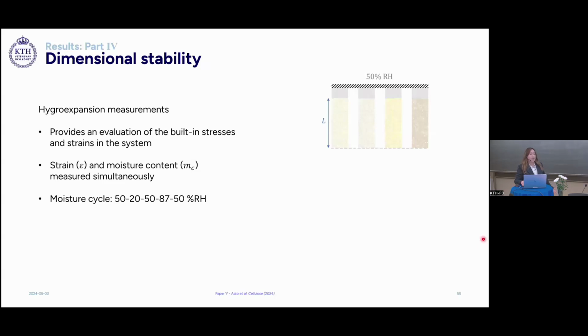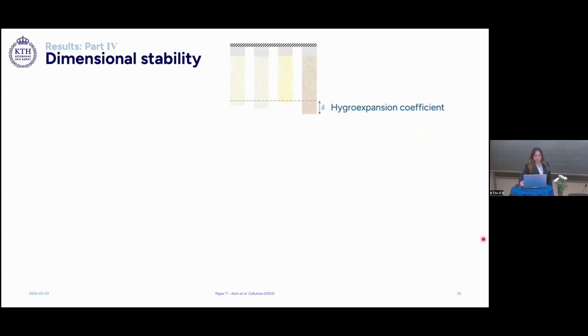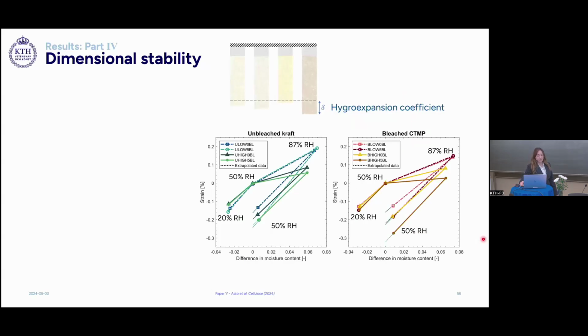In order to investigate the effect of moisture on the properties of the paper sheets, we performed hygroexpansion measurements by exposing the papers to different cycles of relative humidity. And hygroexpansion measurements provide evaluation of the built-in stresses in the network. And here, the strain and the moisture content were measured simultaneously. The hygroexpansion coefficient relates to the slope of the presented curves.